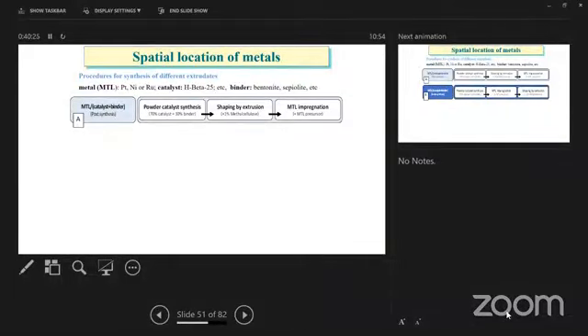what we do, we have the powder of the catalyst, then we do shaping by extrusion. So once again, this is the mechanical mixture of the catalyst, meaning the zeolite and the binder, and we do shaping by extrusion. We also add the organic binder, methyl cellulose, which is then removed after calcination. And then we do impregnation of the metal. So we do impregnation then of the extrudates.